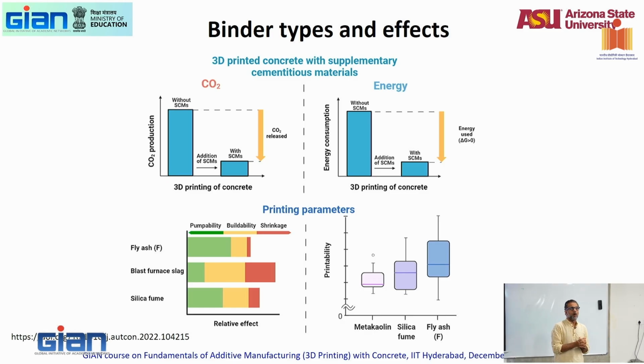So given a certain yield stress that you have to achieve, by replacing cement, fly ash is a good option, correct? Now, what if I want to increase the yield stress? I accidentally added quite an extra amount of fly ash. Now, I want to increase the yield stress. What particle will you add now to increase the yield stress? Slag, maybe. Why slag? Very angular particles, right? So it might be beneficial, but its angularity is very comparable to cement. So it's not going to really do too much different from what cement does. What's your next option? I can add aggregates. Yes, if I want, I might add some sand. I might add some angular coarser particles, right? So I might make it into a mortar to get a slightly higher yield stress.